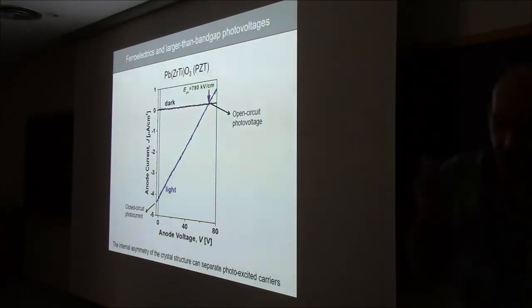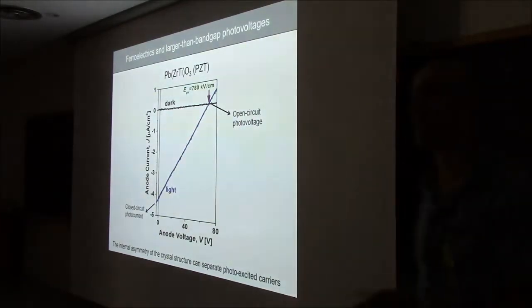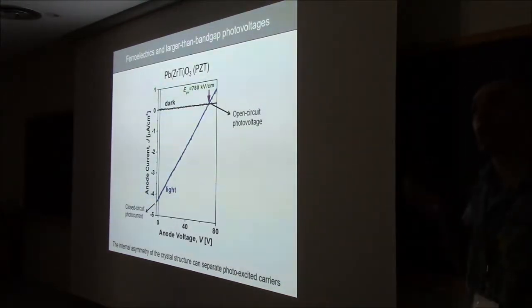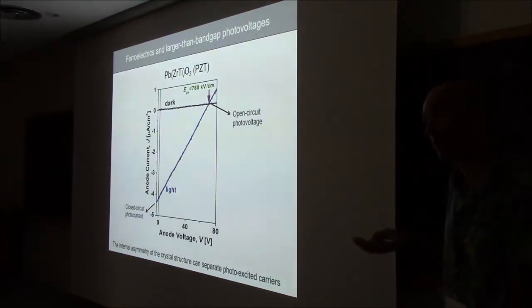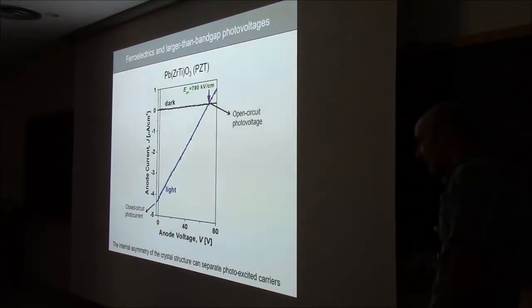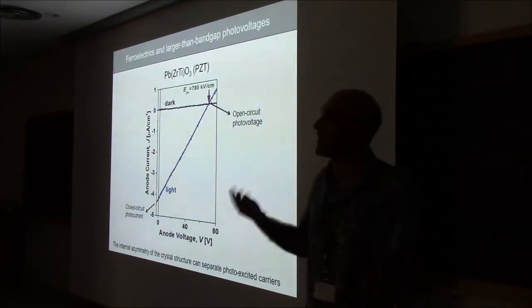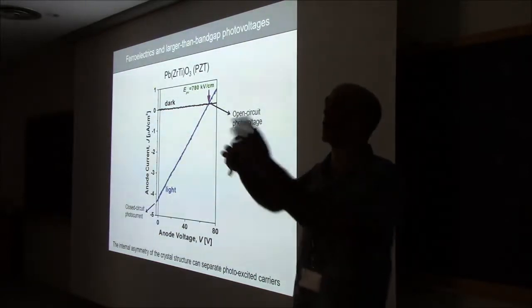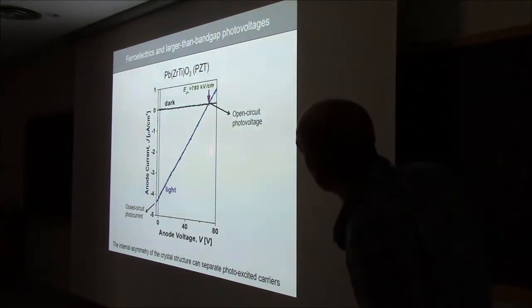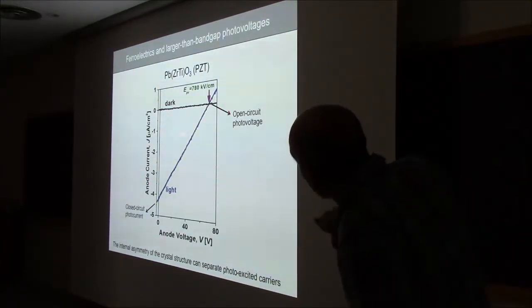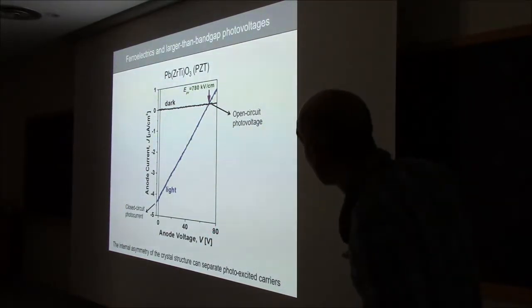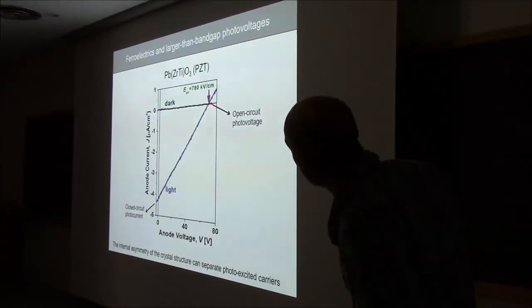Because it's not an effect due to band bending, but by something intrinsic to the lattice, it's not limited by the band gap of your material. So whereas the normal photovoltaic effect is basically limited by the band gap of your two semiconductors that you're using in your solar cell, in ferroelectrics this is not the case. You can get photovoltages that are huge. Okay? This is an experiment that we actually did in our lab. Ferroelectric thin film with one transparent electrode, you shine light, and the open circuit photovoltage is tens of volts. You can even measure more than 100 volts.